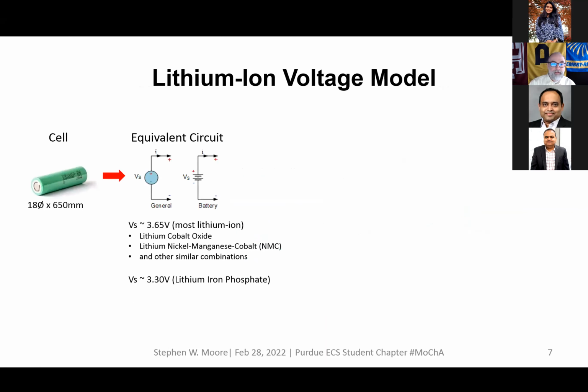So looking at a single cell, the easiest possible model for a single cell is simply a voltage source. Most lithium-ion cells, the one in your cell phone, the one in your watch, or these 18650 cells that I have shown in the picture, usually have cobalt-based cathodes, and they run about 3.65 volts average. There's lithium cobalt oxide, lithium nickel manganese cobalt, and other combinations. And then there's a lithium iron phosphate cathode material, which runs about 3.30 volts.